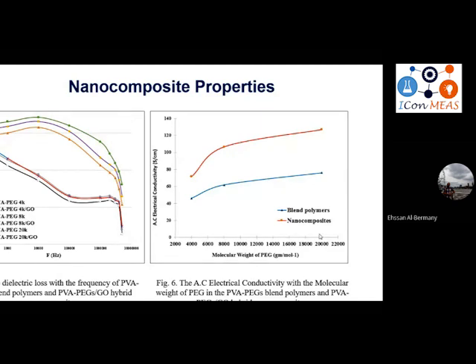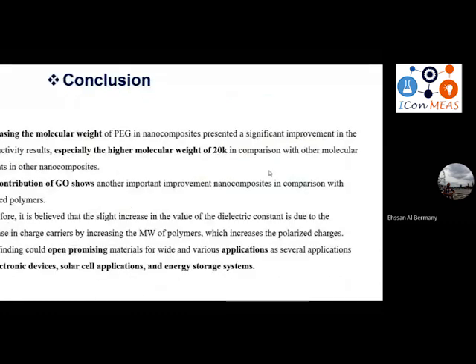With the increase in the molecular weight, we can see that for the blended polymer, the AC increased, even when we use graphene oxide. There is not a big difference between these values. The nanocomposite with the graphene oxide has a strong effect even with an increase in the molecular weight. So basically, these materials together get significant and important properties, and they also have an impact on the materials.